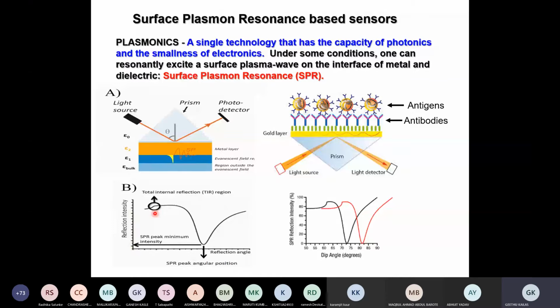Okay, you can change the angle and then monitor this. And as I mentioned earlier, if you have a gold coating over a dielectric, it is very much possible to attach antibodies to the gold, and these antibodies are ready to accept or bind antigens. In that way, when the dielectric medium is changing here, you will find the condition for this SPR is changing and it occurs at a different angle. So you will find a change in the position of the angle. You may be familiar with these experiments. I am just introducing it as a sensor.